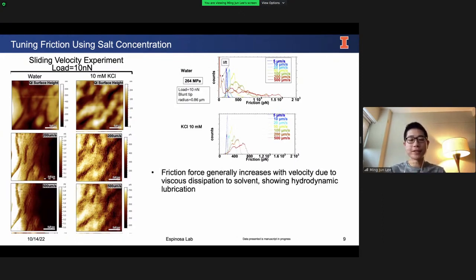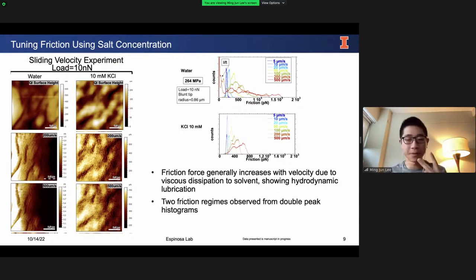And what I'm seeing is that friction force generally increases with the velocity. And I believe this is due to just viscous dissipation to the solvent. The faster you slide, the more energy you lose to the solvent. And it's a feature of hydrodynamic lubrication. What's more interesting is that I'm seeing 2 friction regimes that are coming out from my friction maps.